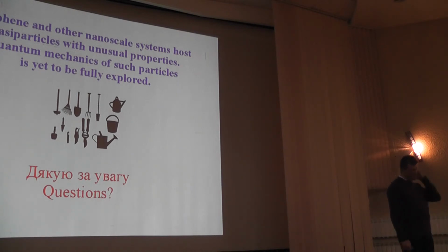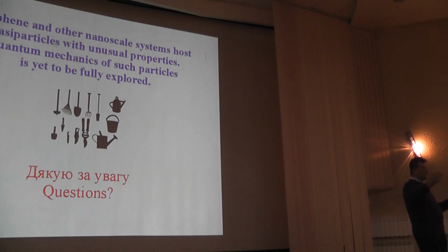Well, but is this because simply electrons would spend more time around? Yes, but in the scanning microscope you still have to see an increased amount of electronic density at the end. Indeed, you can look at the energy and the width of the resonance, and the width of the resonance is roughly 1/7 of its energy. So it basically means that the electron makes 7 motions in, out, and in, out before it leaves the state. So yes, that's the time separation. That's very easy. Thank you.